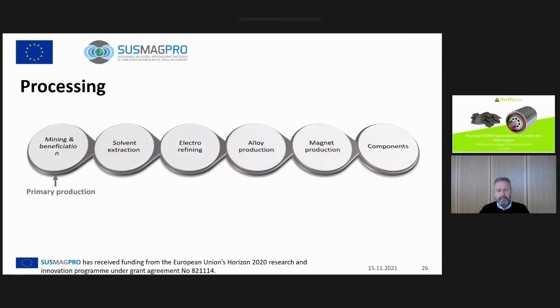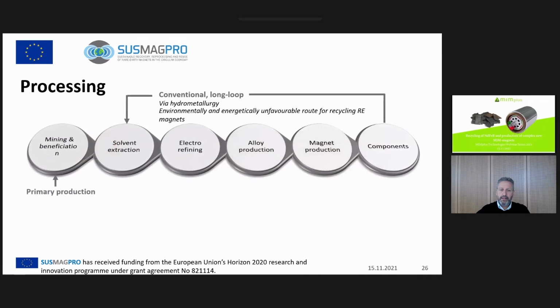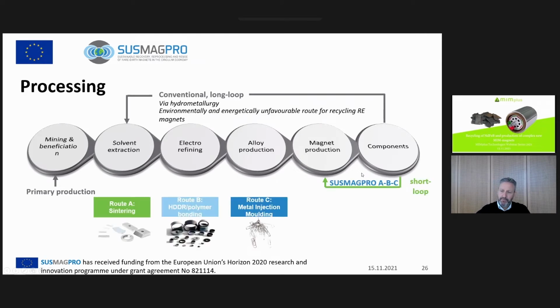And so compared to the primary production, which goes from the mining to solvent extraction and refining to the alloy and the magnet production, and then the component, and also compared to conventional recycling, where you go via hydrometallurgy back to the neodymium or the dysprosium, and then go through refining and the alloy production, the magnet production again, our route with the hydrogen allows us to do a short loop recycling because we keep the alloy as a magnet powder, which allows us to make sintered or polymer bonded magnets, or what Johannes is talking about today, metal injection molding.